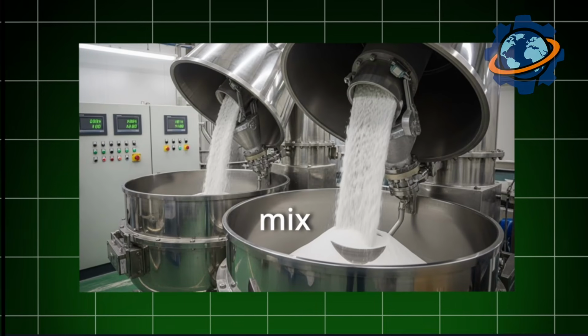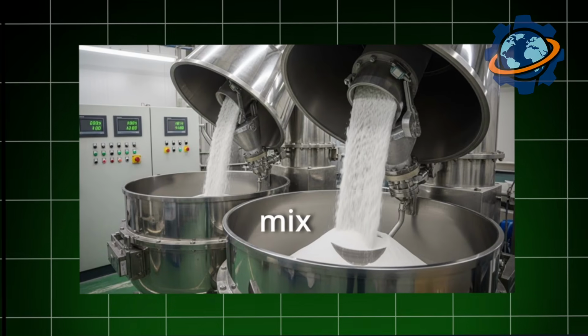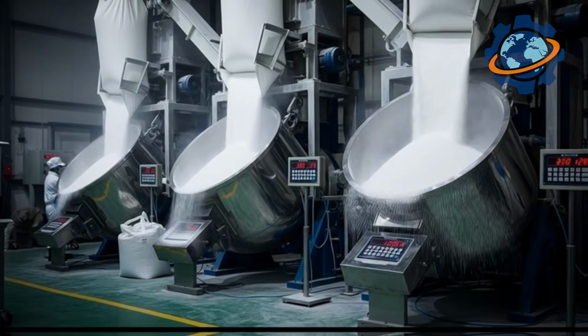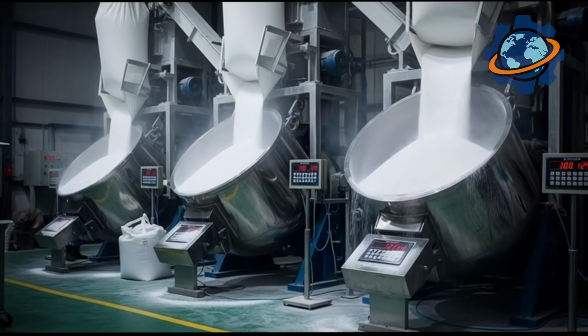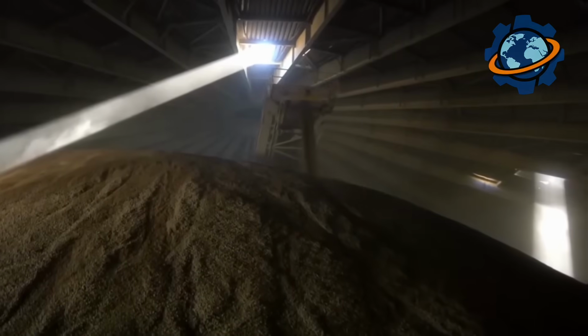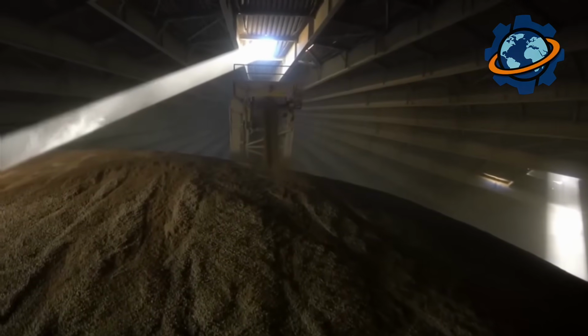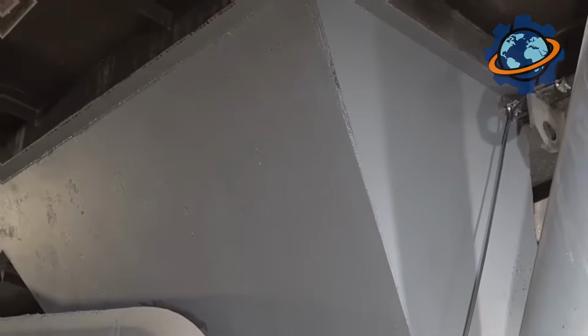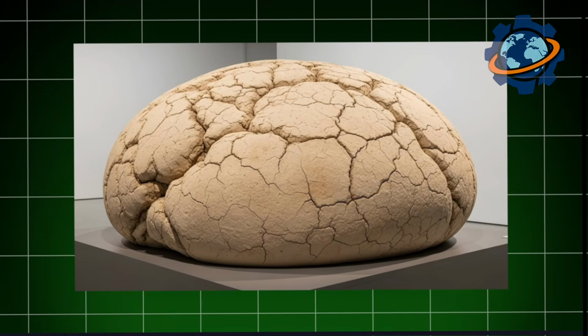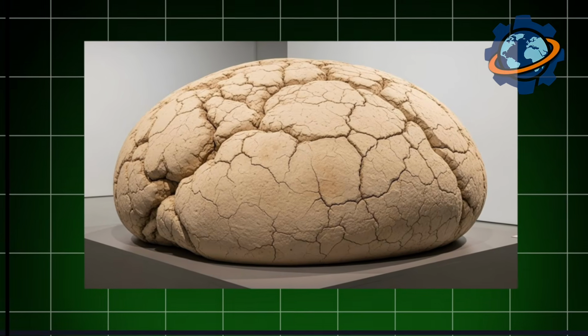In giant mixers with a 500-gallon capacity, powders are combined in precise proportions. They add liquid wax-based lubricant, 5 or 7% by weight. The mixer spins for 30 minutes at 50 revolutions per minute, transforming dry powder into a uniform wet mass, like bread dough. Temperature is held at 100 degrees so the lubricant doesn't freeze. The result is raw dough weighing 1,100 pounds, ready for forming.